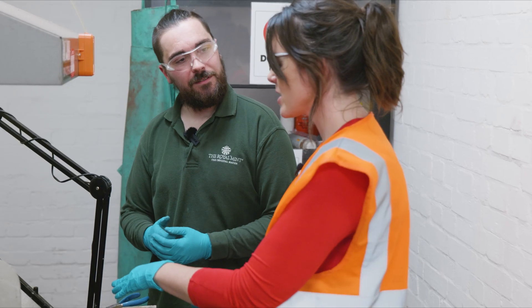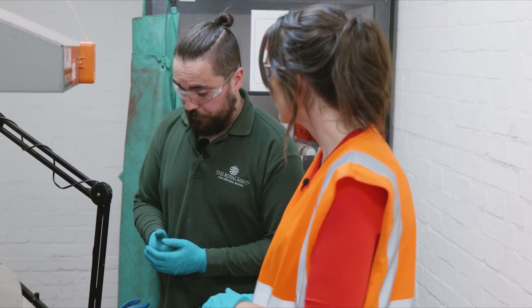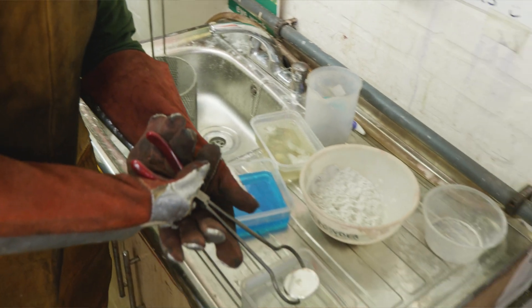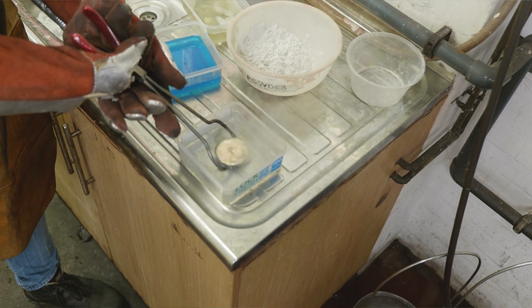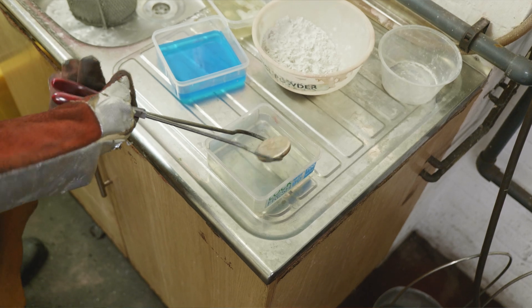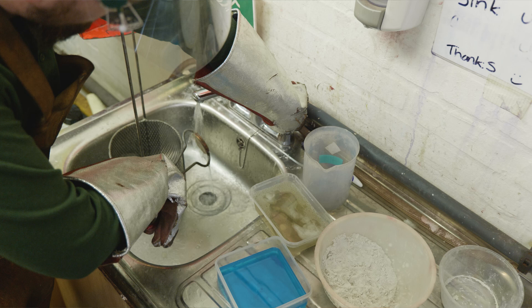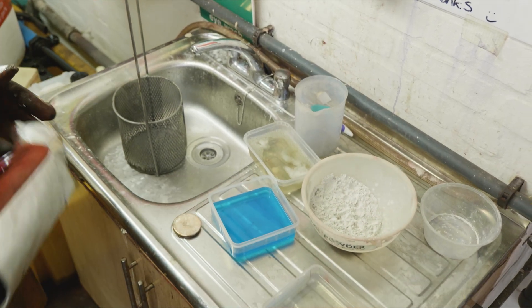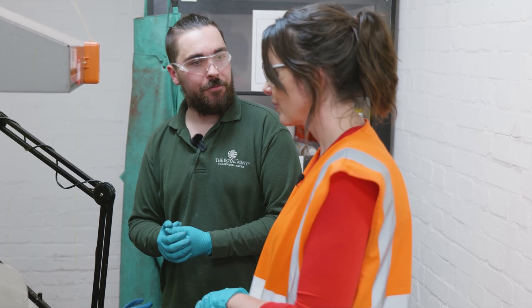So we've got the button here — does it cool immediately, or do you have to wait a few minutes before you can lift it out of the mold? What we do is use a little pot or bath of sulfuric acid — I believe it's about five or ten percent. We dip it in there while it's hot, because the sulfuric acid likes to eat all the dirt or anything from the crucible or from the material itself. So the button does come out relatively clean — that's the best way we cool things.